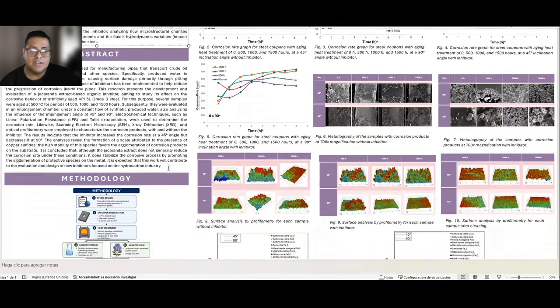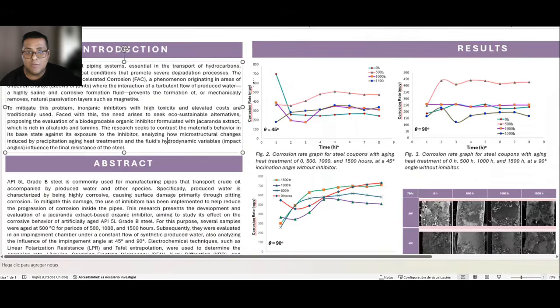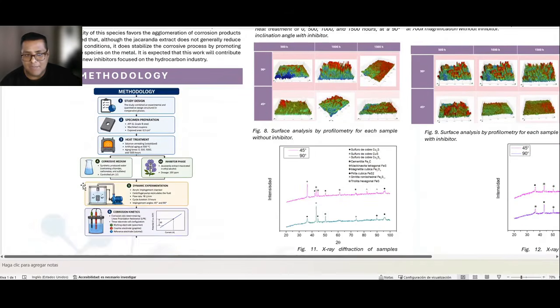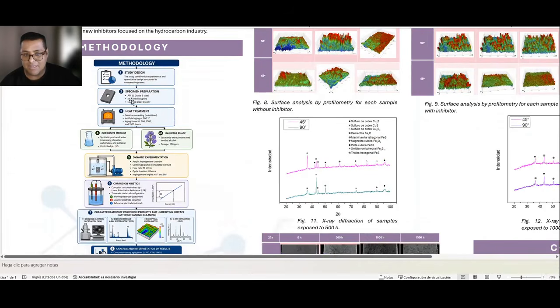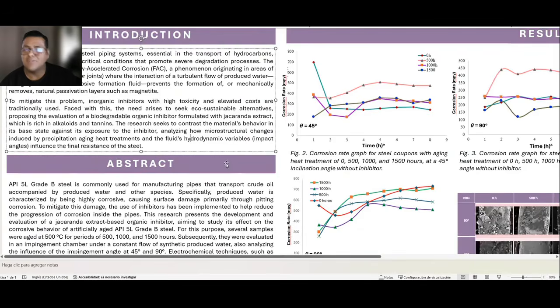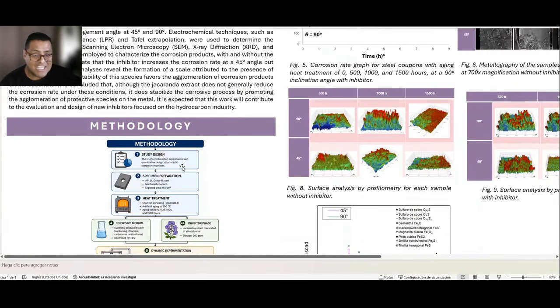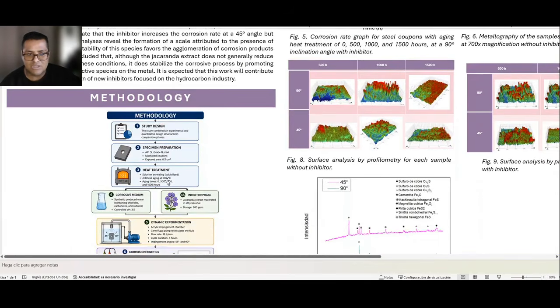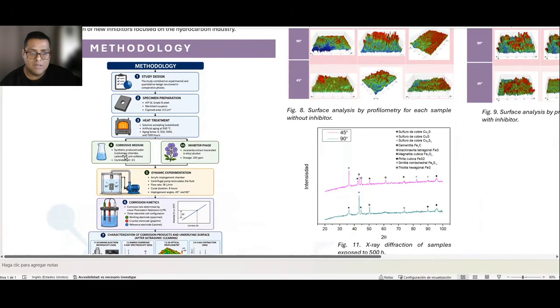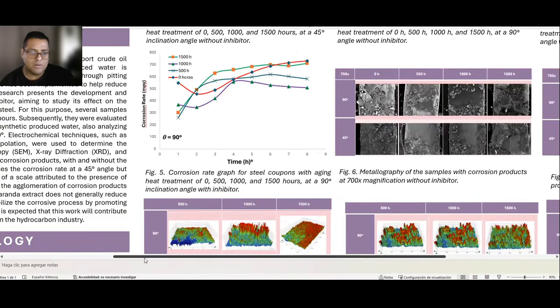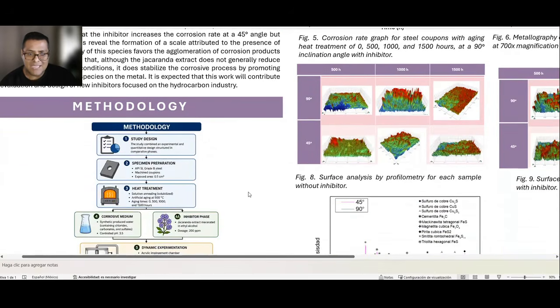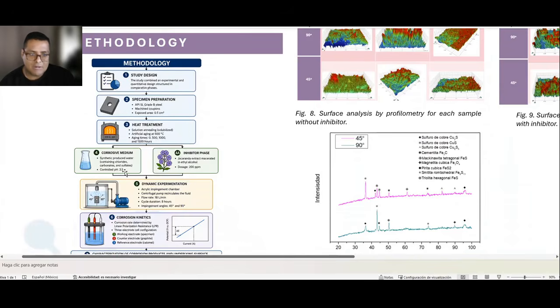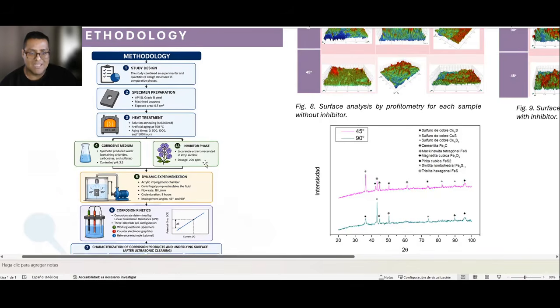Moving over to methodology, we designed two comparative experiments. We machined coupons of the API 5L Grade B steel and applied a solution annealing treatment, followed by an artificial aging heat treatment at 500 degrees Celsius for different periods: 0, 500, 1000, and 1500 hours. The corrosive medium was synthetic produced water at pH 3.5. For the inhibited phase, we added 200 ppm of Jacaranda extract macerated in ethyl alcohol.